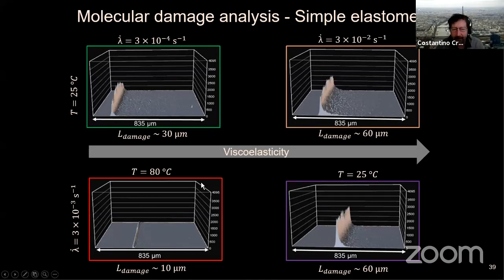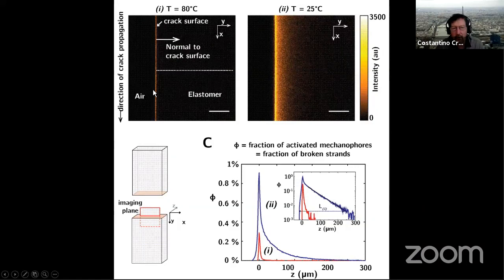This is taken from the paper and shows you what happens at the crack surface. So this is the interface. Here it says air, but for the measurement, it's glycerol. You have here the signal as a function of the crack surface. You can average that over the propagating crack. You can see that for these kinds of cracks in simple material, it's quite straight. So it's easy to average.